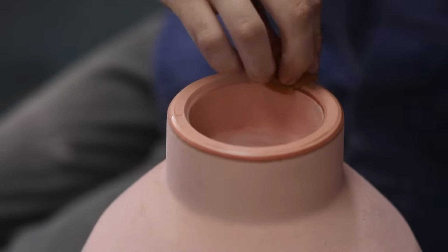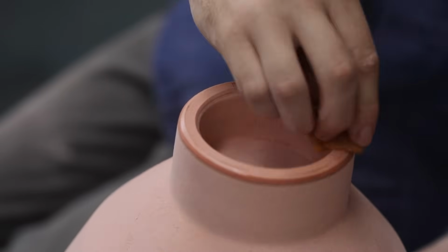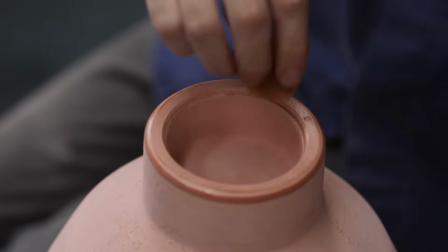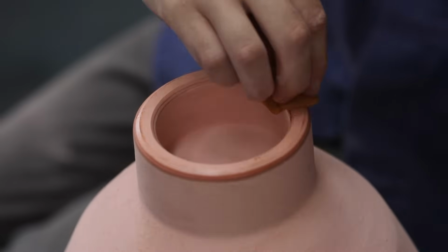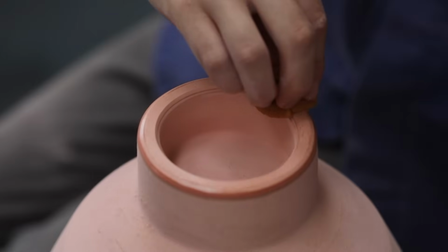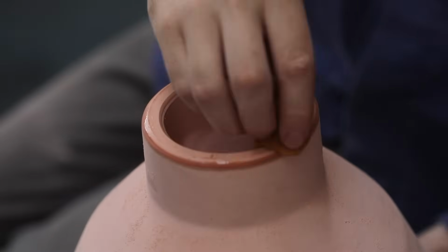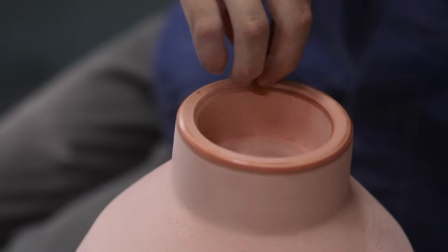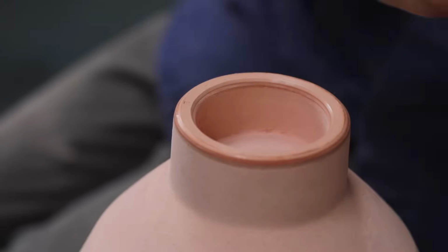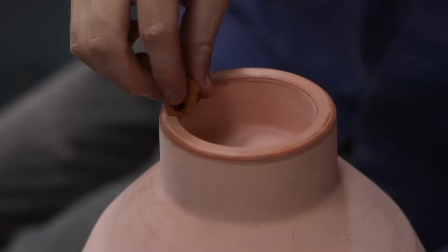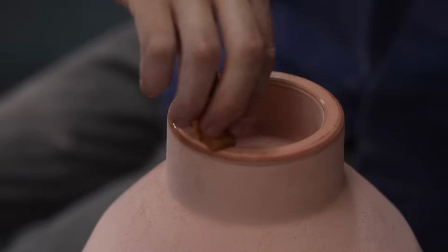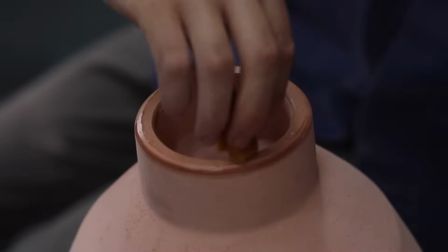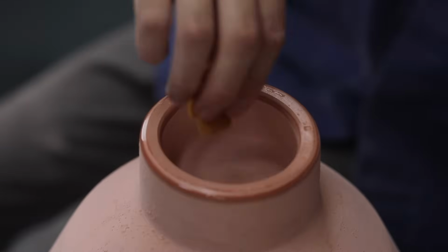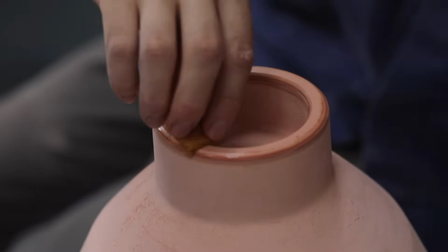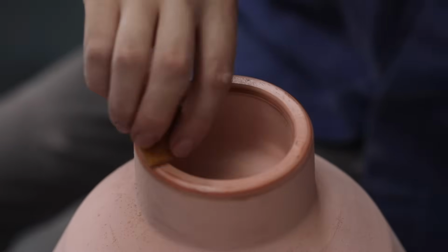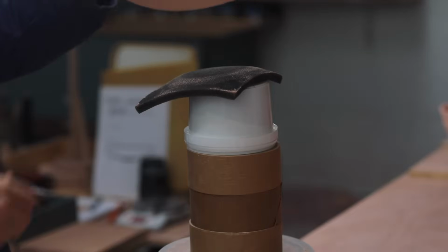I should mention, if you're watching this and you've been glazing pots and you want to tidy them up, not every glaze in the pottery world can be worked in the same way. In fact, you may tidy your glazes up like this, only to find that the tongue marks are still present, and where you got the glaze saturated with water, it's changed colour and texture slightly. All of this is to say that how you clean your glazes up can really depend on the type of glaze you're using, the clay body, and how it's fired, which means this way of doing it may not necessarily work for you. And the real key to success is just trial and error, to find out which specific methods work for you.